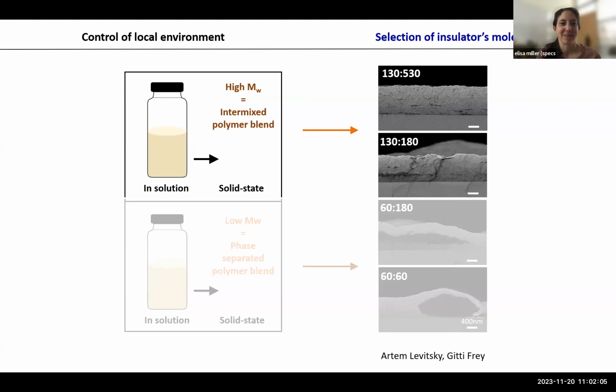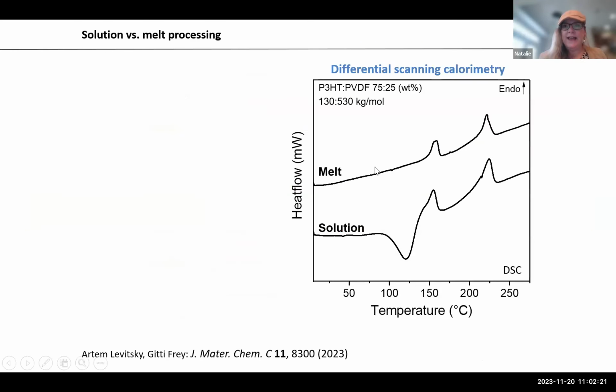Natalie, on that note, since you mentioned if you take it to the melt they phase separate, do you think they might phase separate if they stay in the swollen electrolyte long enough, because it sort of plasticizes the chains? I think plasticization is not good enough, because even here, I actually was angry with Henry. He wanted to immediately go to the melt to phase separate. And I said, no, don't worry. Once you get here to this cold crystallization peak, it will be fine. Henry should have bet with me. It was not fine. So I think plasticization will not be sufficient.